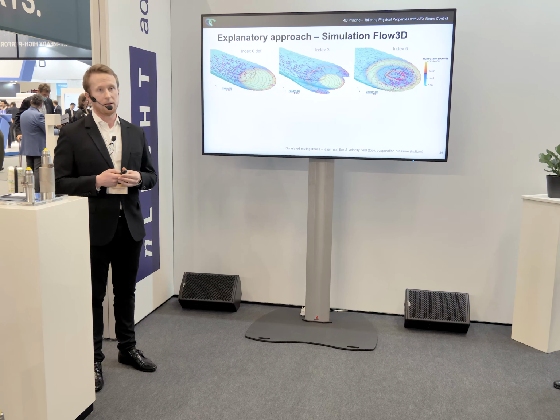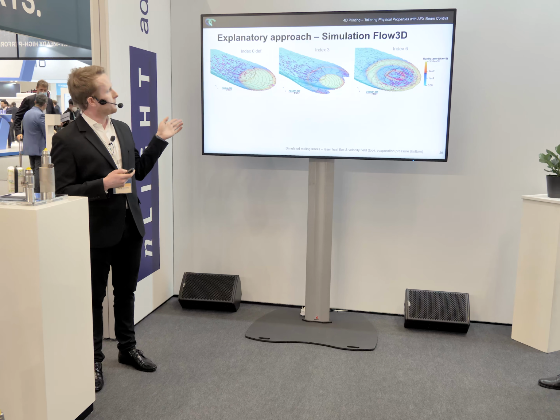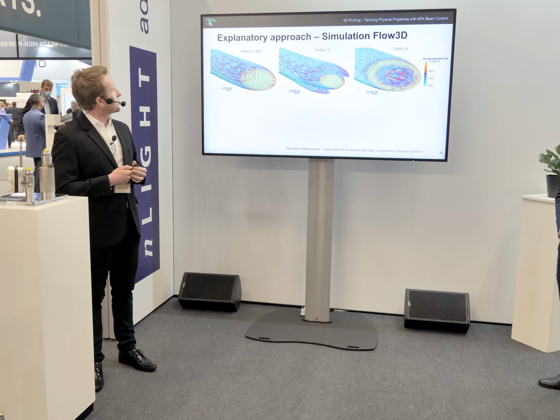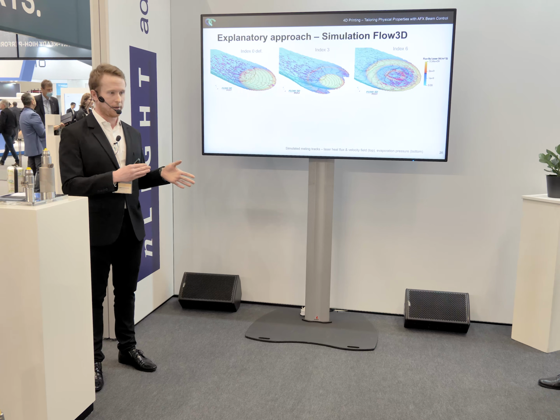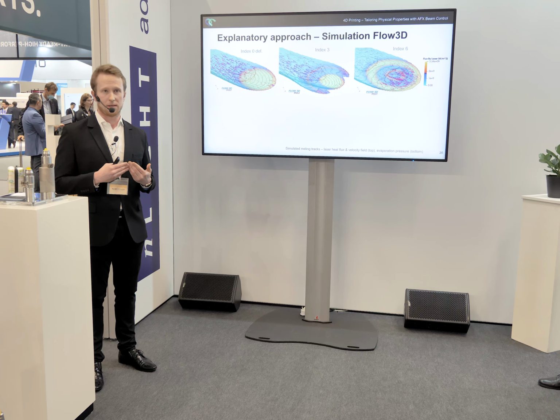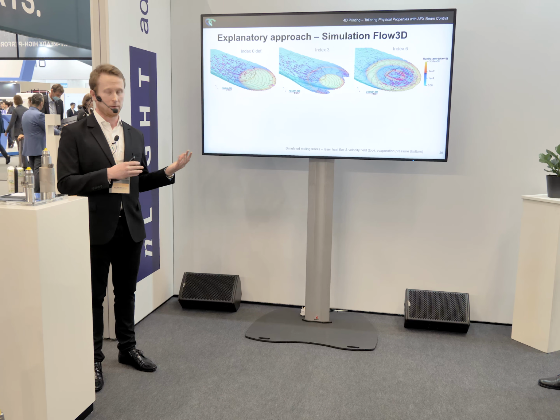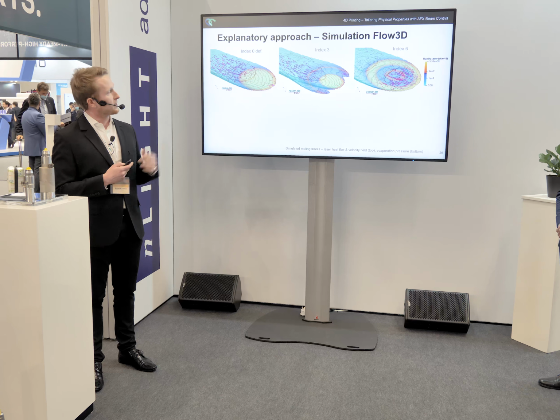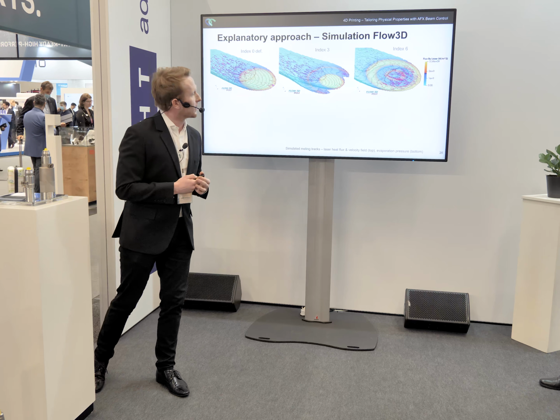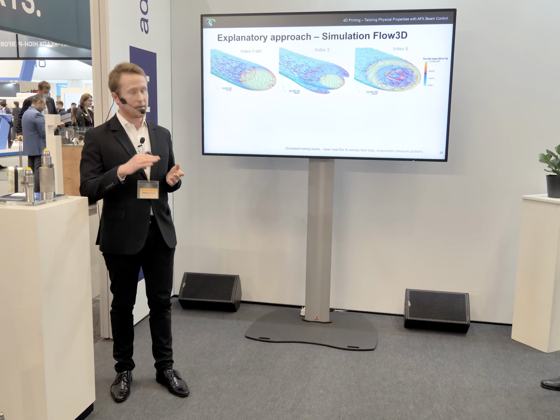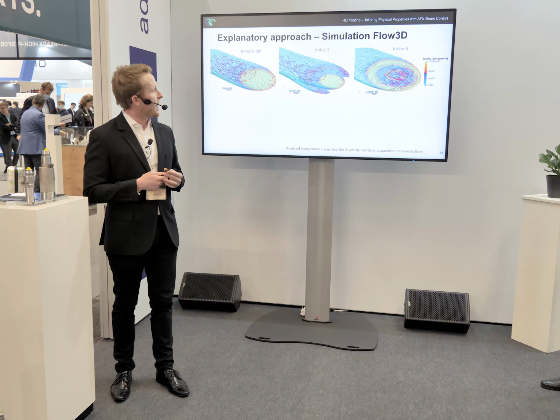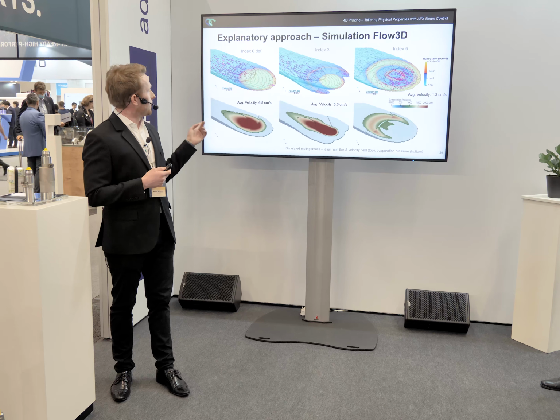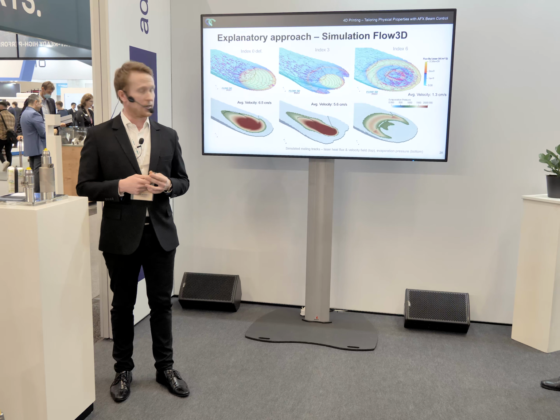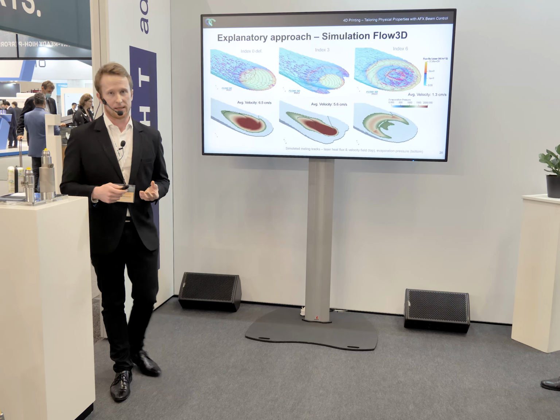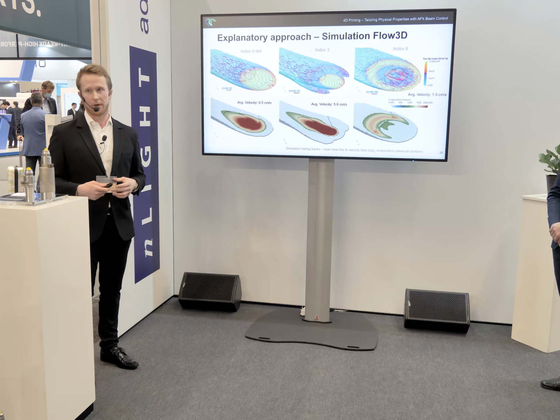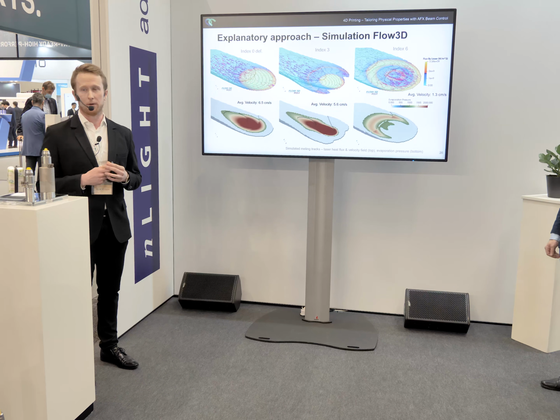What we can see here is that the velocity field for index 0 and index 3 shows that most of the velocity vectors are directed to the back of the laser beam, or sort of to the behind of the melt pool. While for index 6, we can see that some of the arrows are also oriented to the front of the melt pool. And in general, the average velocity inside the melt pool is lower for index 6, which also corresponds to a more stable behavior of the melt pool and less spatter of the material.